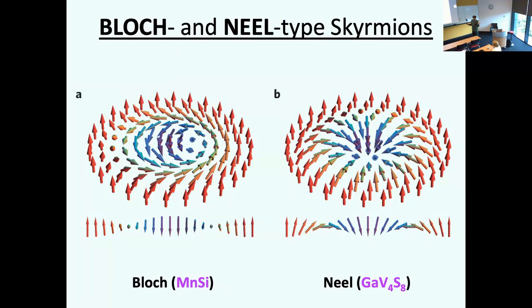So this is some vector field configuration. In this case, magnetic spins, but it doesn't matter. The spin is down here, and as you go out, you have all the spins going up. So this is called a Néel skyrmion. If I cut it this way, it's a cycloid. So you remain in the plane. And there are materials like gallium vanadium sulfide, which actually harbor Néel skyrmions. Now you can comb it, you get this skyrmion, which is topologically equivalent, and this is called a Bloch skyrmion, in manganese silicide materials. Now, if I cut it this way, the domain wall is helical. So this is called a Bloch domain wall, okay?